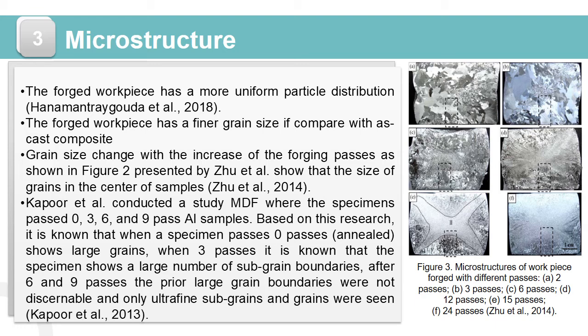Based on this research, it is known that when a specimen passes 0 pass, it shows large grain. When 3 pass, the specimen shows a large number of subgrain boundaries. After 6 and 9 pass, the prior large grain boundaries were not discernible and only ultrafine subgrain and grain were seen.